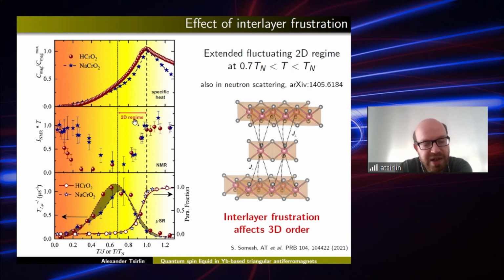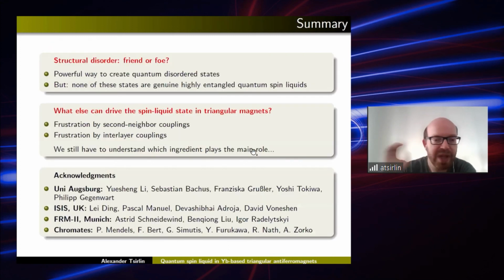So the interlayer order does not develop down to this point, and only below this temperature the different layers start to order. Also in neutron scattering, there is evidence for the same kind of behavior. And that's why we think that the interlayer frustration can really seriously affect the three-dimensional long-range order. So when you have these shifted magnetic layers, then they may have some problems to order. And then you may have the situation where there will be magnetic order within each plane, but there will be no macroscopic long-range order. So with this, I come to my summary.